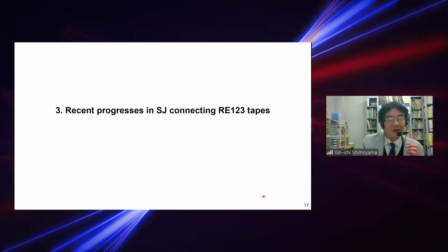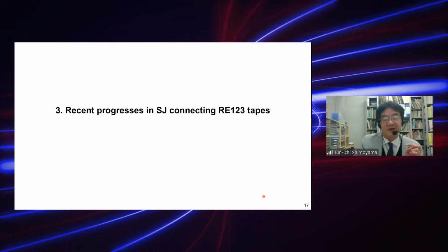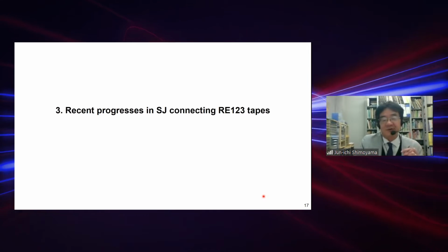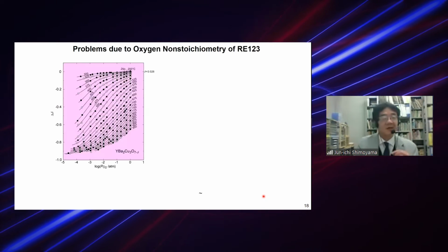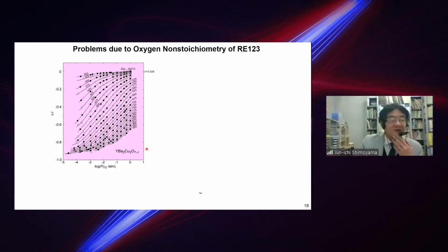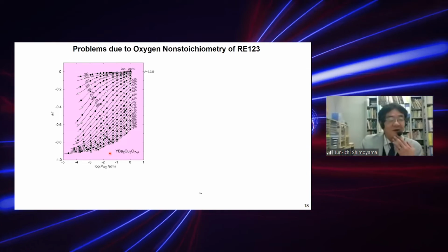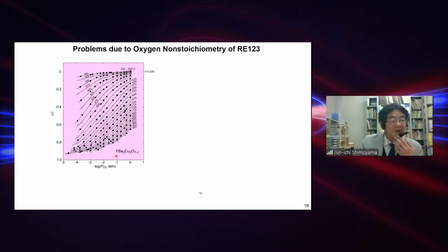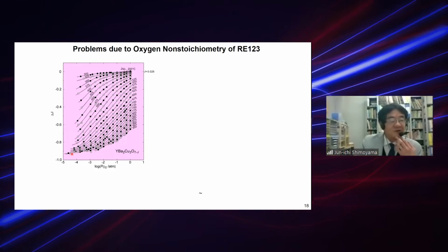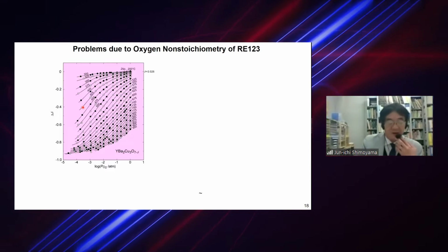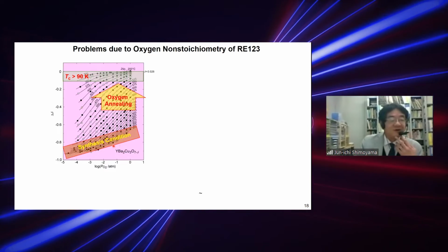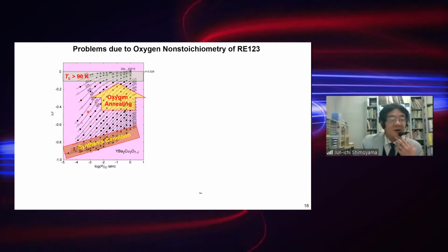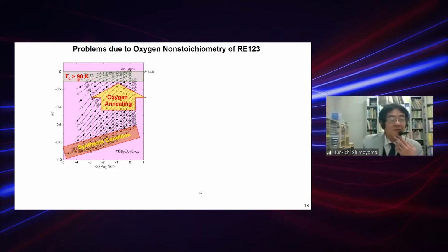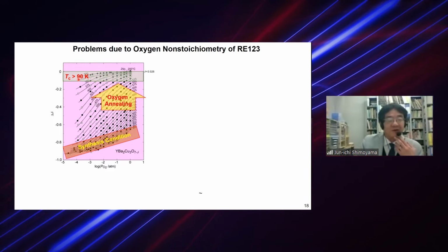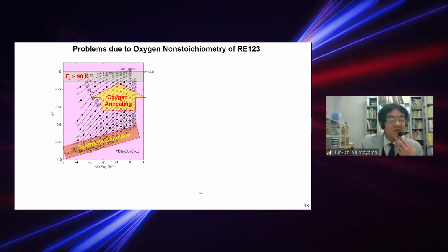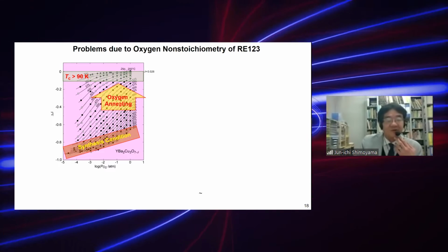From now, I'd like to show the recent progress in the superconducting joint connecting RE-123 tapes. Most of you know that the RE-123 system has very large oxygen non-stoichiometry, with oxygen content from 6 to 7. So this is the synthesis condition. However, to obtain 90 Kelvin class superconducting properties, we must increase the oxygen content by oxygen annealing.